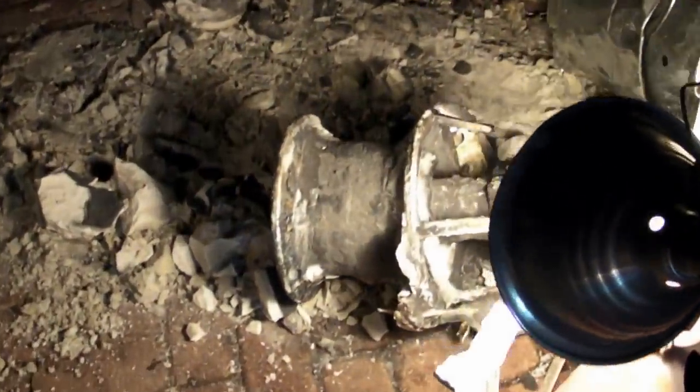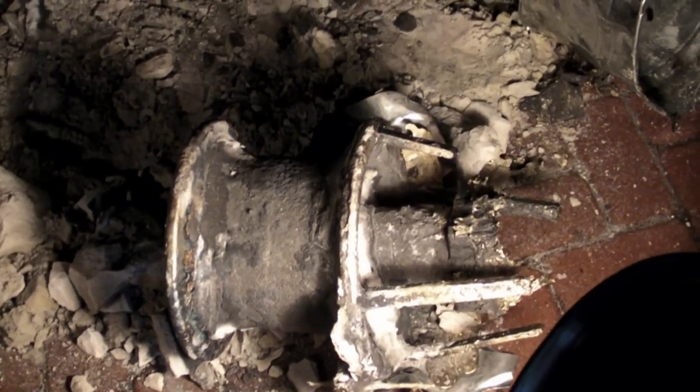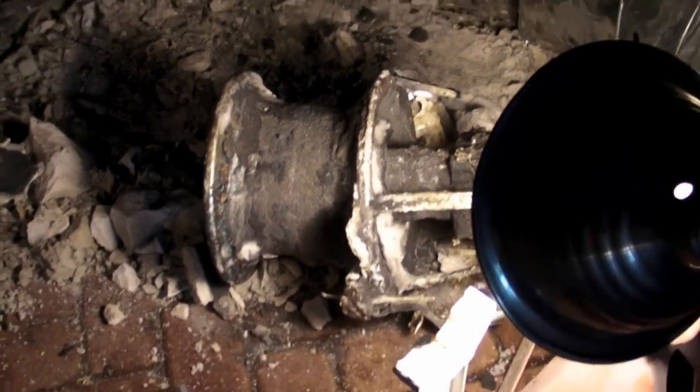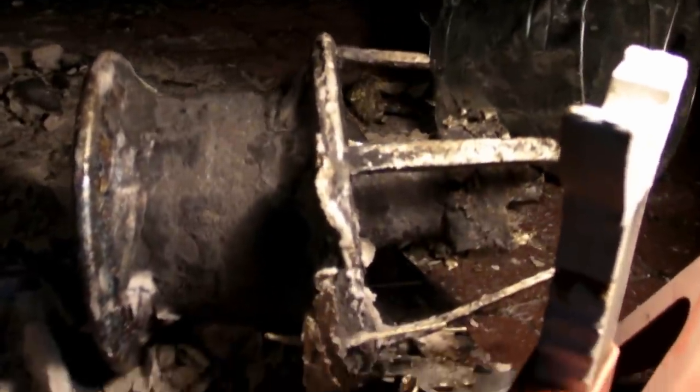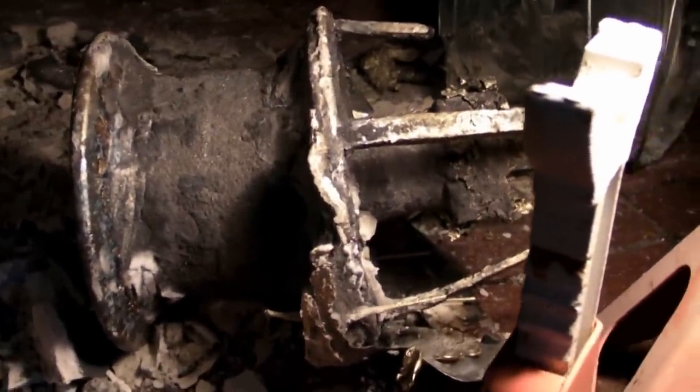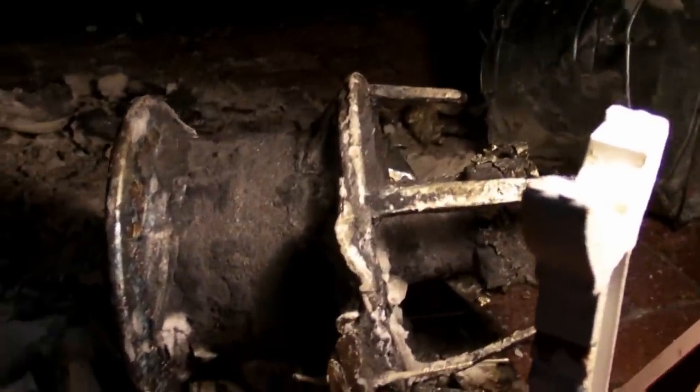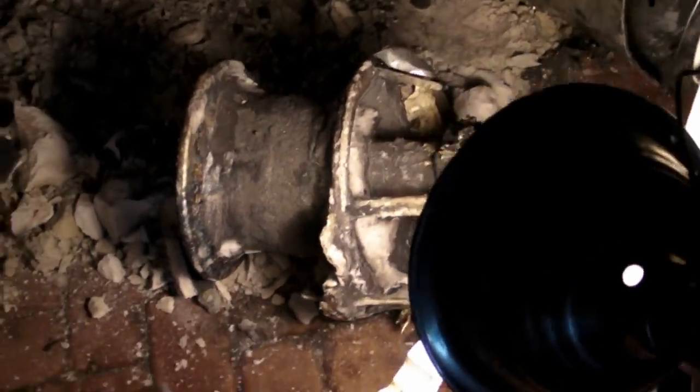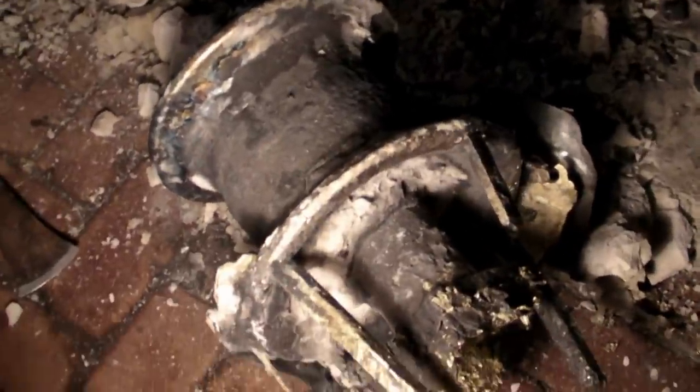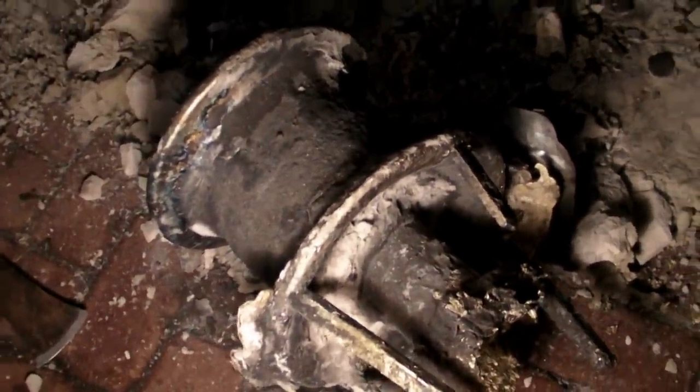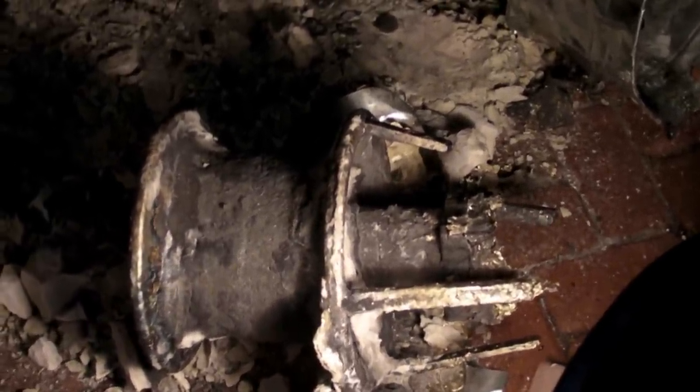Well, it's too bad we didn't film it because we lit Kay on fire. Just a little bit, a little singed around the edges. We're going to blister here. That's the dangers of lost foam casting. Learn not to stand downwind. Gauge the wind before you start. But it blew out the side of the mold because the buckets really didn't leave enough sand at the top. It filled the riser up and then it blew out. So we don't know. It could be you're looking at an abortion, in which case we're sorry. And it could be you're just looking at a newborn child, which they're kind of ugly too. It really is ugly.